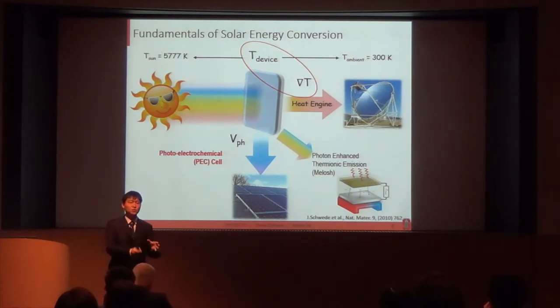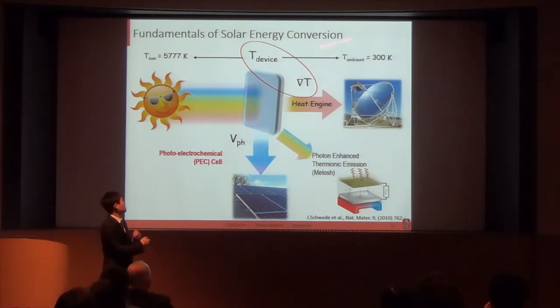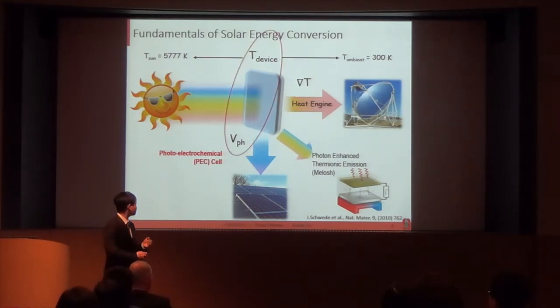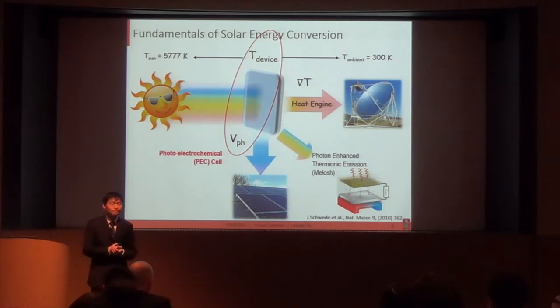Just by carefully choosing this device temperature, you not only create such a gradient, but also facilitate certain processes in solar energy conversion, such as the thermionic emission in a thermionic converter or the chemical reaction in the thermochemical cycle. However, it is not common to combine the temperature of the device with the photovoltage driving force. In fact, in solar cells, it has been proved that increasing temperature only decreases the efficiency.